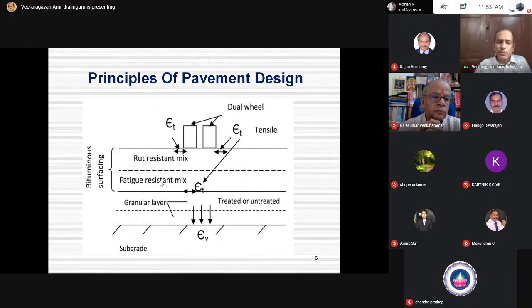But many researchers do a fatigue testing on what material? They'll say bituminous concrete. I always say bituminous concrete should be a rut resisting mix. Why are you testing it for crack resistance? This is again another area that has to be explored. So fatigue resistance is by the binder course. Rut resistance is by the wearing course. We also consider the vertical compressive strain on top of the subgrade, and we think that this is related to the rutting in the layer.